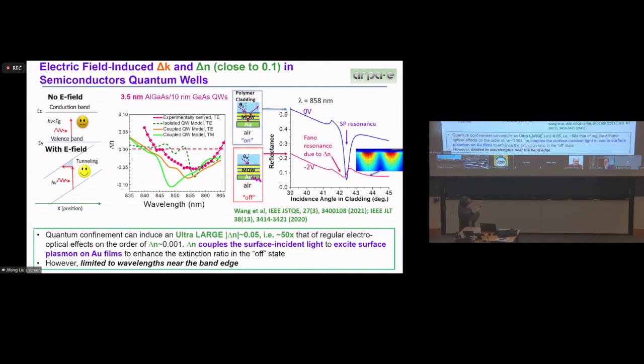But if you turn on this electric field, not only is the multi-quantum well opaque, but also, due to this refractive index change, you match the propagation of the surface plasmon on the surface of this gold film. So essentially, you dump energy not only into the absorption of the quantum well, but also to excite the charge oscillations on the surface of gold. So that increased your extinction ratio here. So that's essentially what we demonstrated in the last couple of years.